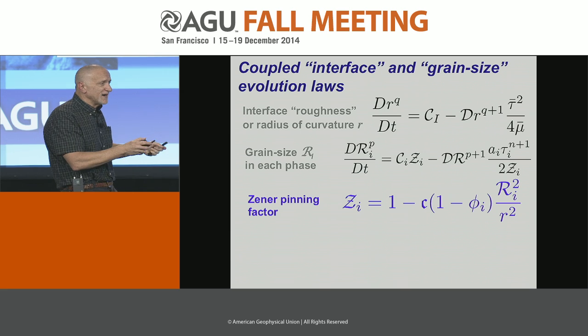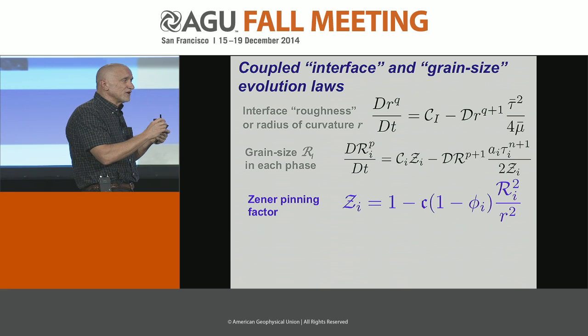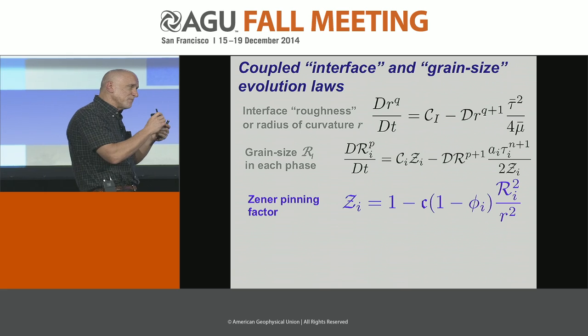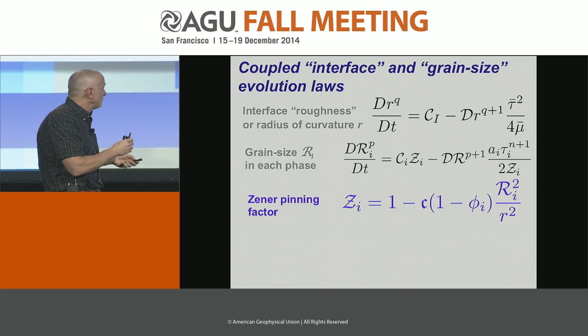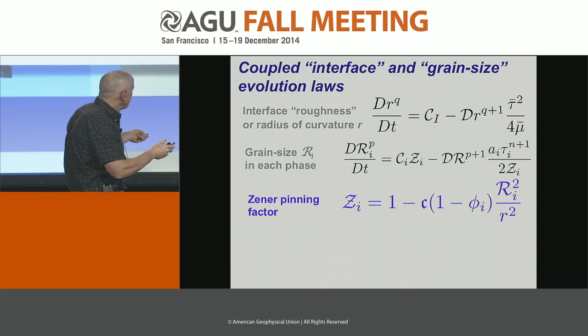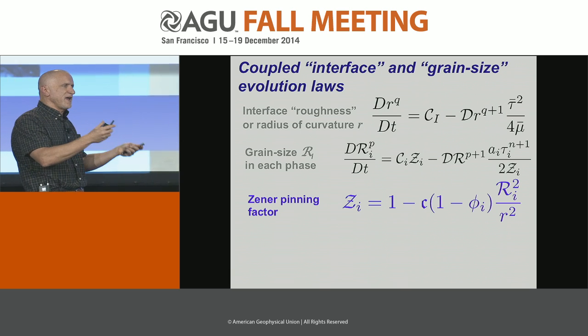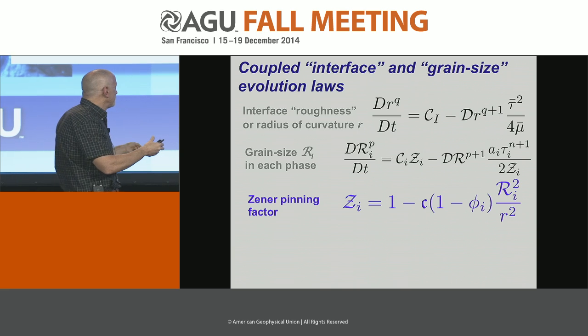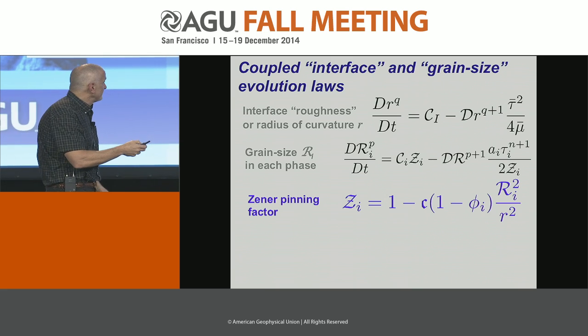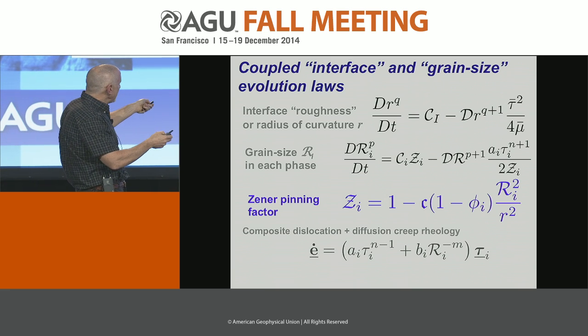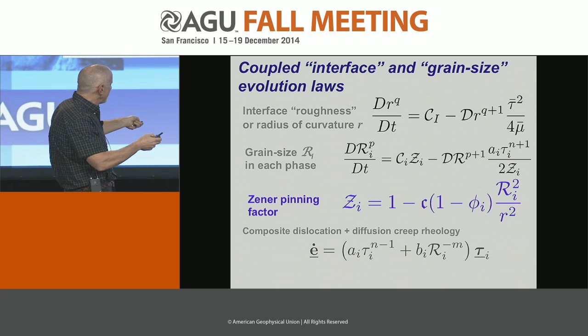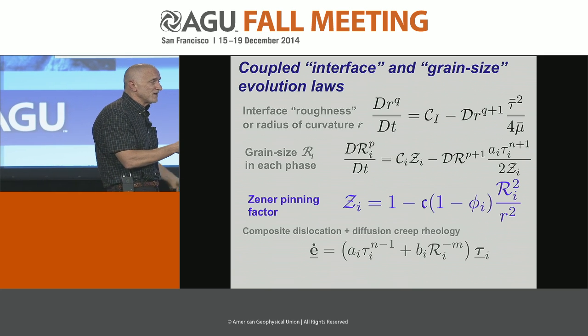But if the pinning bodies or the radius of curvature of the interface is very small, so the pinning bodies are small like the little blue blobs I showed before, then it will cause more pinning. If this is 0, it's pinned, means you shut down grain growth, and you can even make it go a little negative to start driving grain reduction. We then take this grain size and put it into a rheological law, strain rate versus stress, but it's dependent on grain size and can be non-linearly dependent on stress.